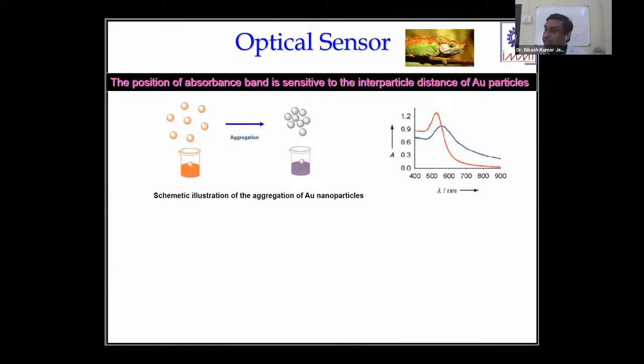But when you synthesize the gold nanoparticle, you are able to get this kind of color, this wine red color. Understand? So you can see how the property changes from yellow to a different color. This is because of the surface plasmon resonance absorbance, and the color depends upon the interparticle distance. You can see this is a different color.